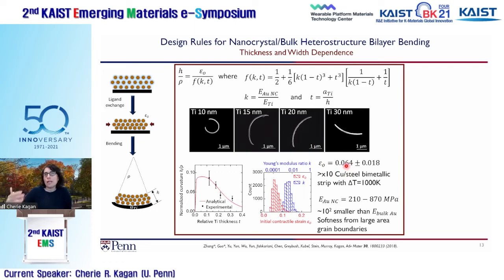And just to give you an example, this is a factor of 10 times larger than you get by heating a copper steel bimetallic strip by 1,000 degrees. And that's just simply through this simple immersion process in a chemical solution. So we create a large misfit strain that really drives this folding. And the other thing is that we learned about what the Young's modulus is of these materials. And what you'll see is that it's under a gigapascal. In fact, it's about 100 times smaller than that of bulk gold, which is about 79 gigapascals. And so what you can see is that these assemblies of particles are softer, really allowing us to get this sort of folding behavior of the materials.